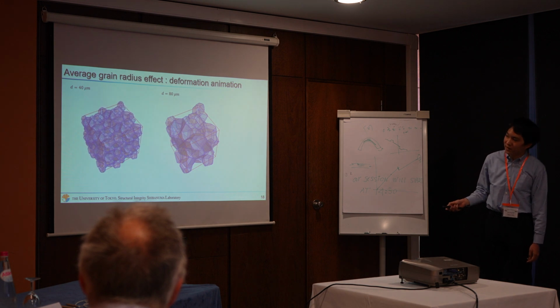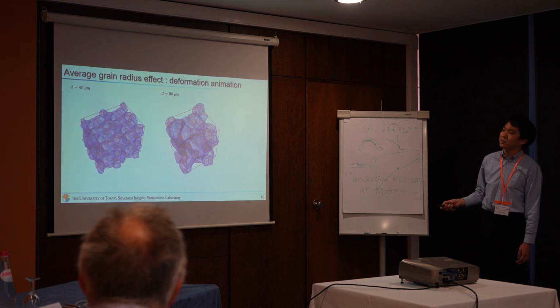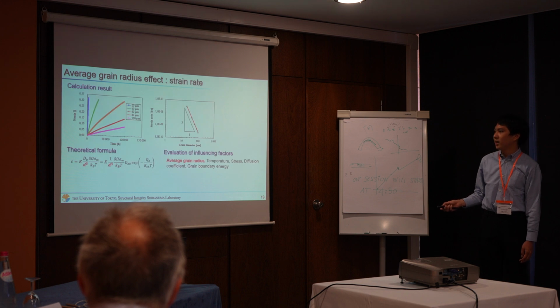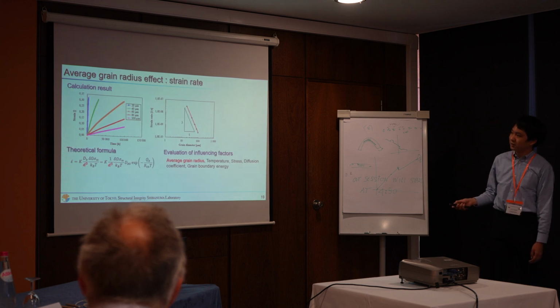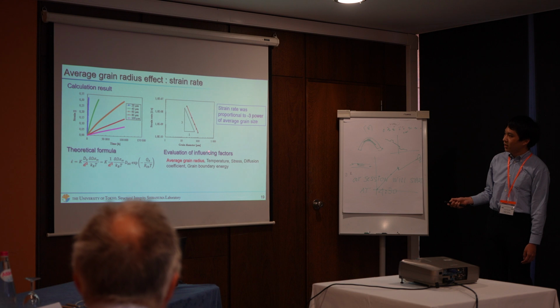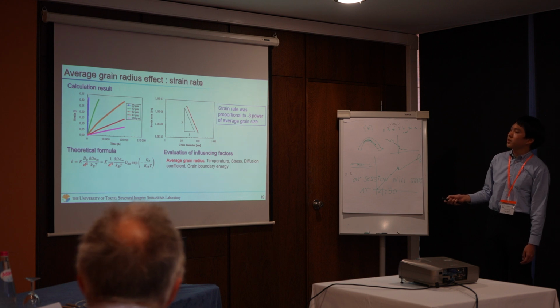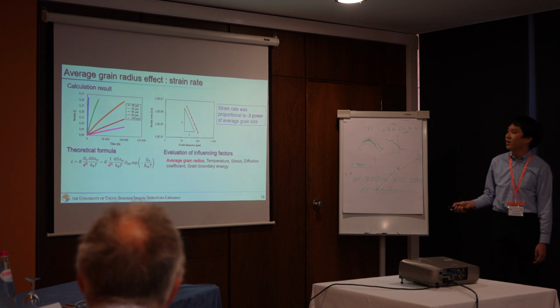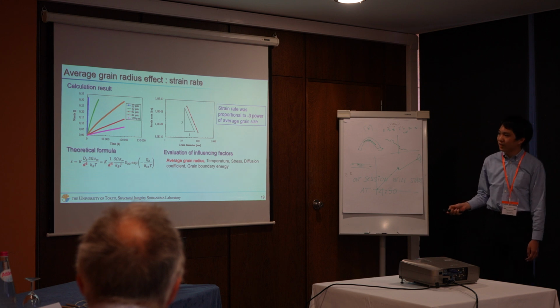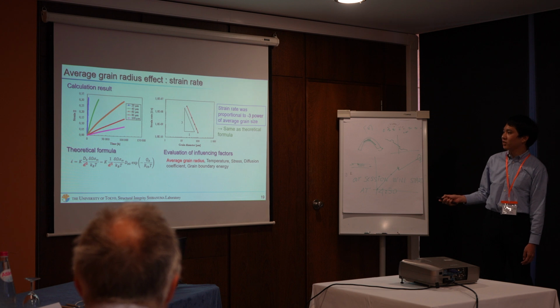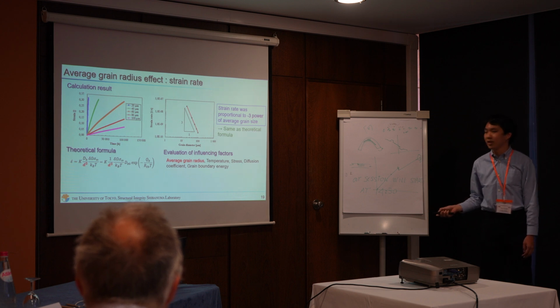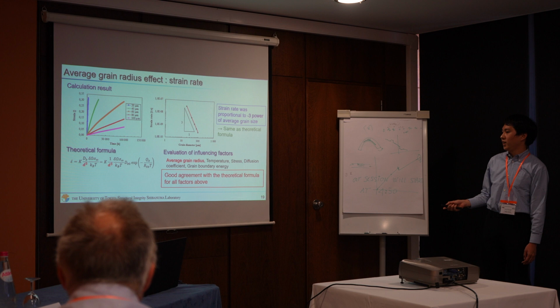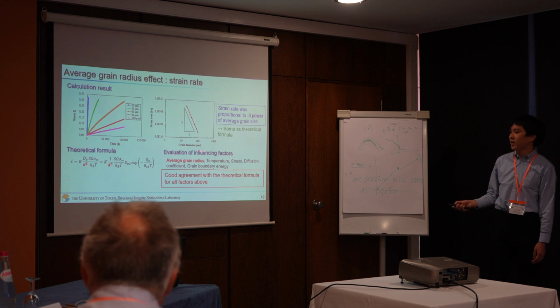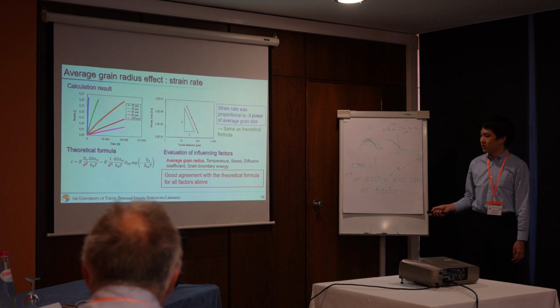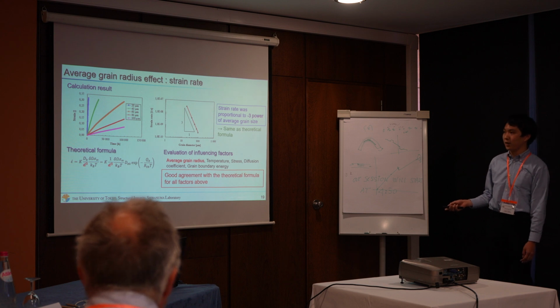It is confirmed that the finer grain deforms faster. And this is the calculation result. As a result, strain rate was proportional to the -2 power of average grain size. And this is a theoretical formula. So this result is the same as the theoretical formula. And for all these factors, good agreement with the theoretical formula is confirmed.